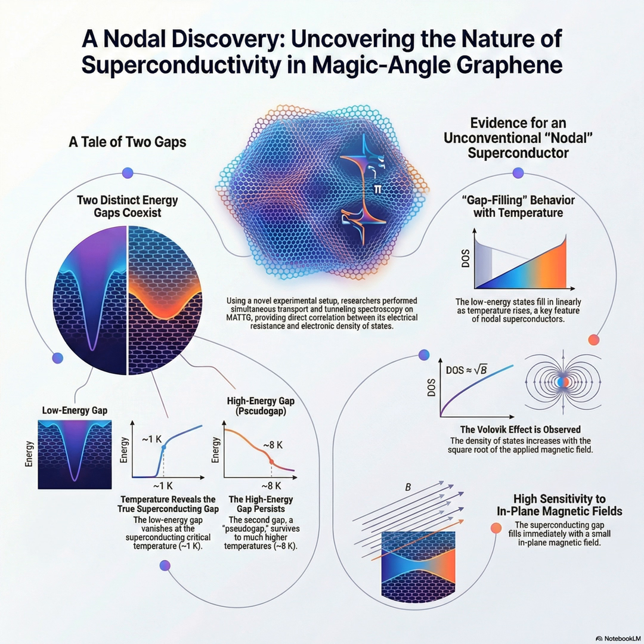And the authors conclude this higher energy gap is not the superconducting gap. They suggest it might be a pseudogap. And that term is significant, right? Because we've heard it in other contexts. Very significant. It's similar to what's observed in high-temperature cuprate superconductors, the materials that work above liquid nitrogen temperatures.